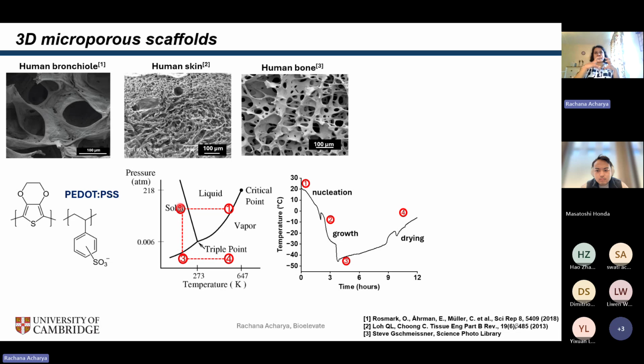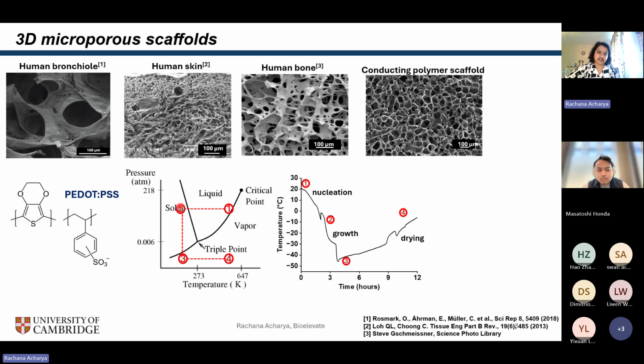And as you can imagine, once these ice crystals nucleate and sublimate, it's going to leave behind this porous structure of the polymer. So this is an SEM image of the conducting polymer after this freeze drying process. And you can see that we have very well replicated this microporous structure of connective tissue.